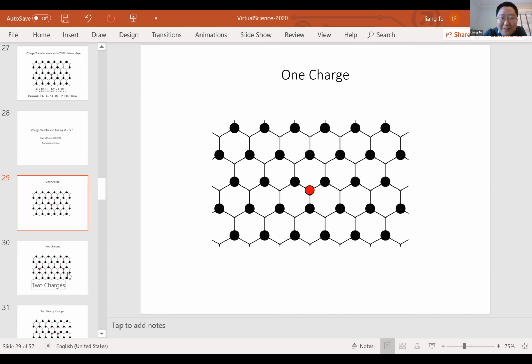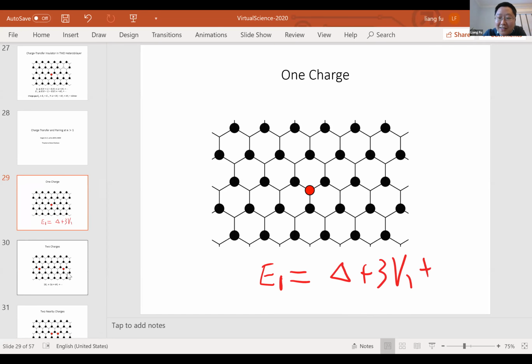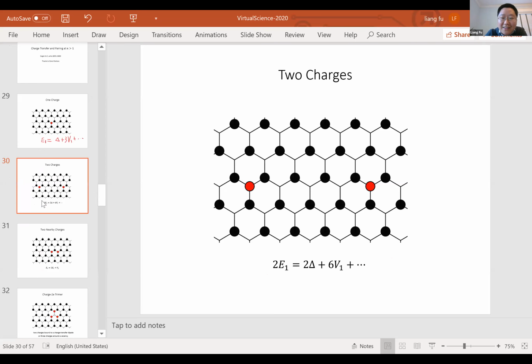Okay, great. So let's consider the energy cost of adding 1 charge to this cation site. Let's call that energy E1. So this is nothing but delta, the on-site energy cost of this cation site, plus the nearest neighbor interactions between its 3 neighbors, which I call 3 times V1, plus longer range interactions. That's clear? Now, let's consider the energy cost of adding 2 charges that are far apart from each other. And that is just twice the energy before. So it's 2 times delta plus 6 times V1.